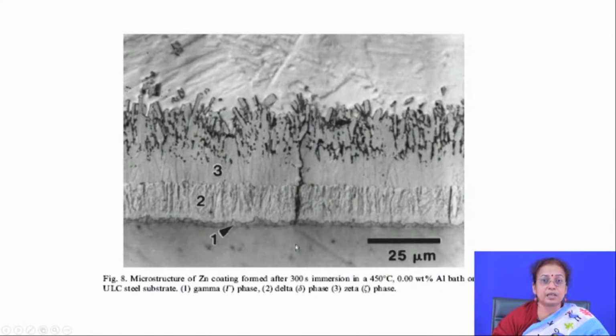So, even though there is crack formation at the interface, you will still find that as zinc is there on the surface, zinc preferentially corrodes, and by that process the underlying steel is saved. But even though that is there, you still find that the overall lifetime of the component gets reduced. So, whatever the fact may be, even though the steel substrate is saved, you cannot really allow this kind of degradation to occur, or these kinds of defects to form at the interface, because it deteriorates the overall service life of the component.